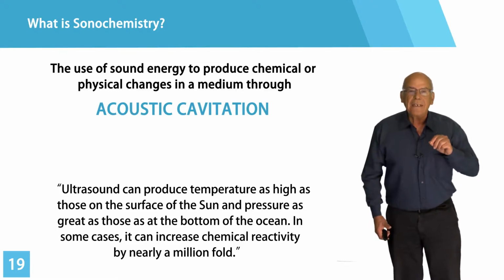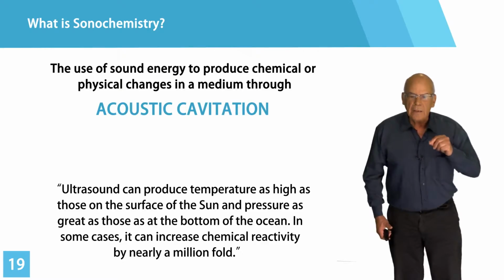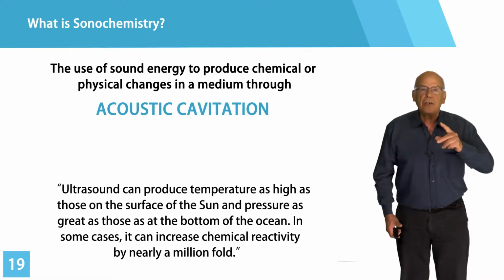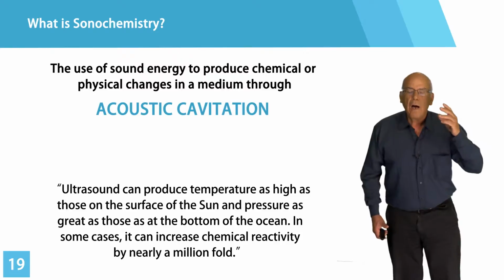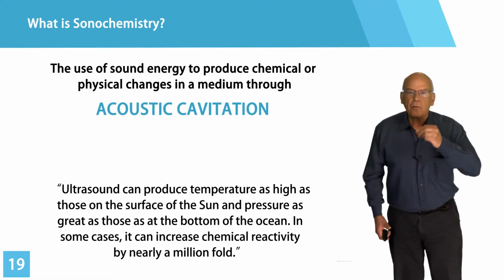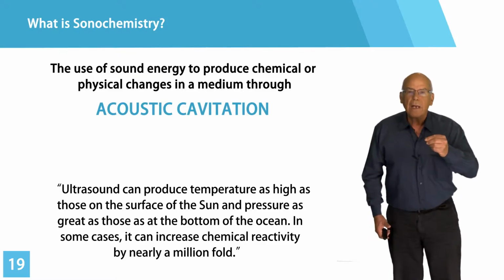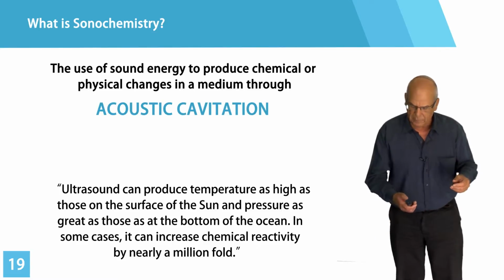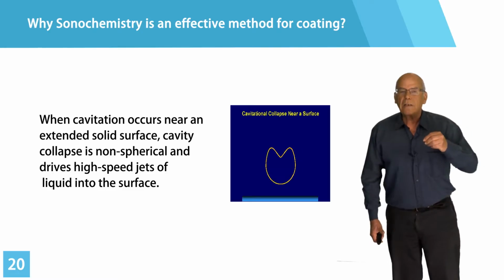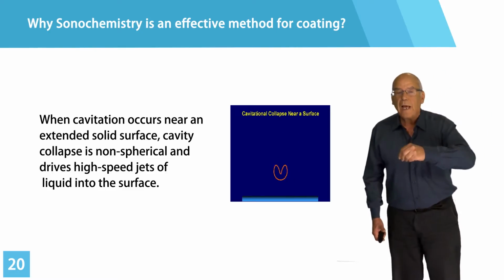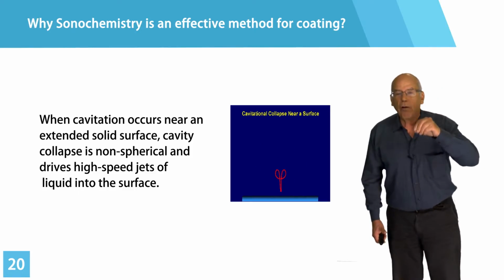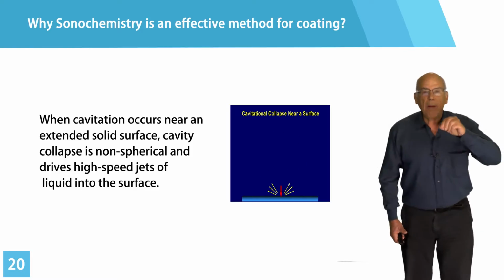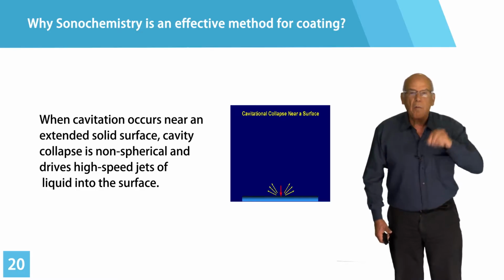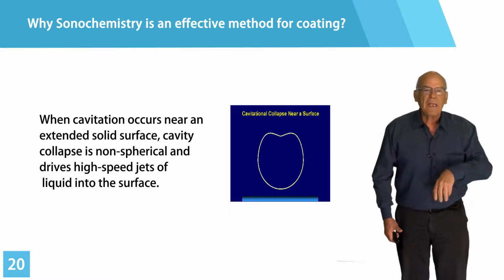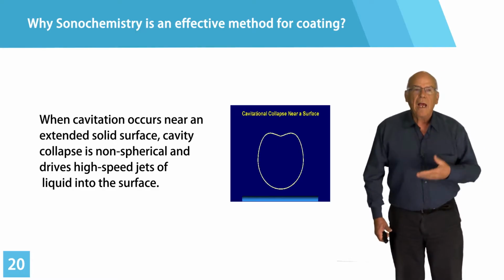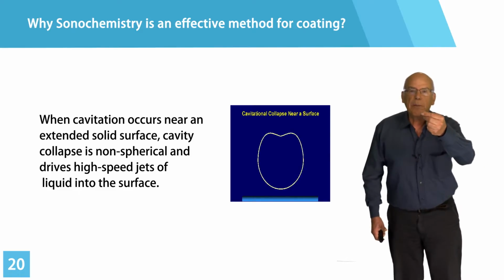Upon their collapse, there is a dramatic increase in the temperature as well as the pressure. The temperature reaches 5,000 degrees Kelvin, along with very high pressures. Under these extreme conditions, chemical bonds are broken and reactions take place. Chemistry is going on. Now, in this project, we are utilizing a special phenomenon involved with the application of sonochemistry. When the bubble collapses near a solid surface, and the solid surface can be a piece of textile, a plate of glass, or a 2 millimeter bead of a polymer.